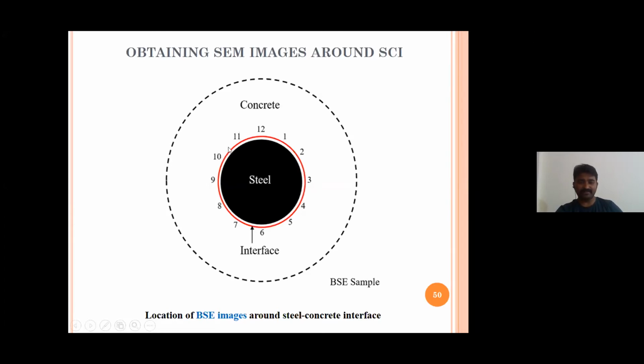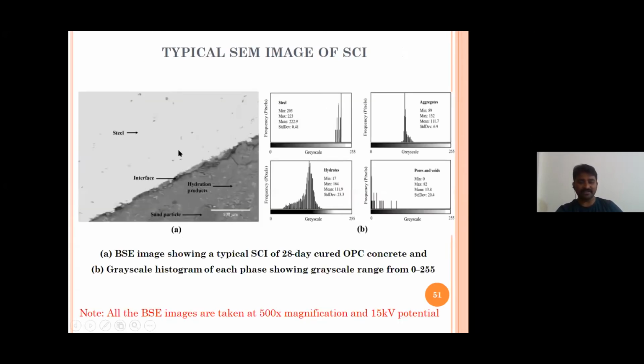For example, at the 11th spot, imagine that I have taken this SEM image. This is my steel. This is the interface. These are the hydration products, and these are some of the sand particles. You may observe a few cracks here also. Those cracks are artifacts of the sample preparation technique. As I'm using a high-speed cutter, it induces some cracks, and it also increases the porous zone thickness. So to avoid these artifacts, we have used a low-speed precision diamond saw cutter.